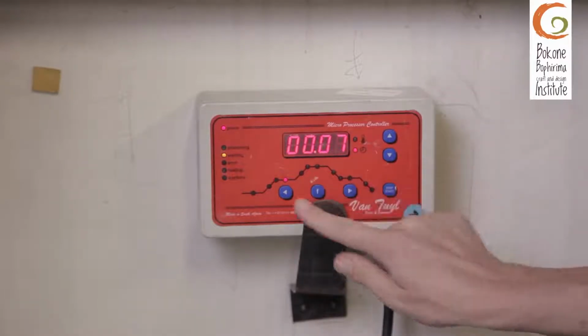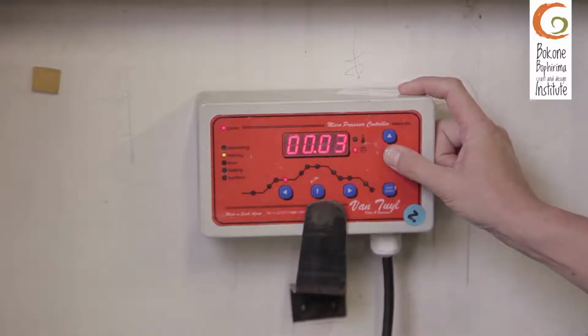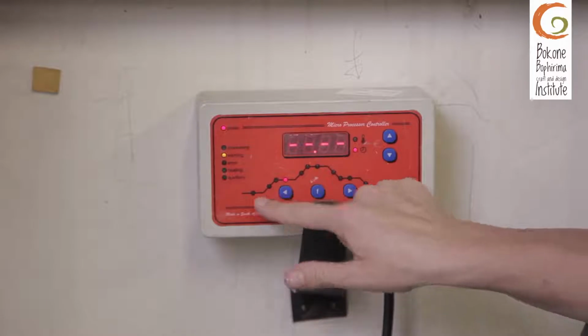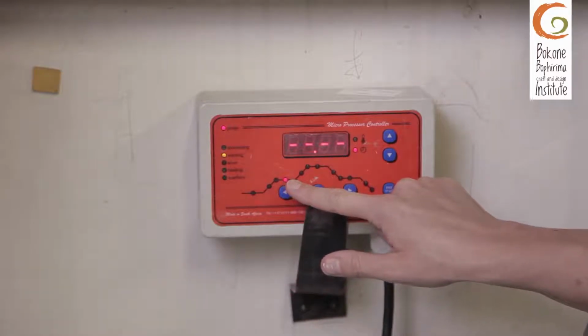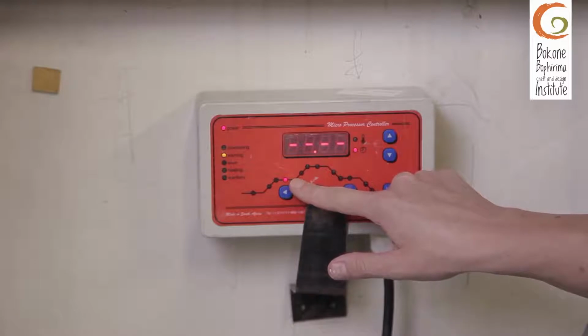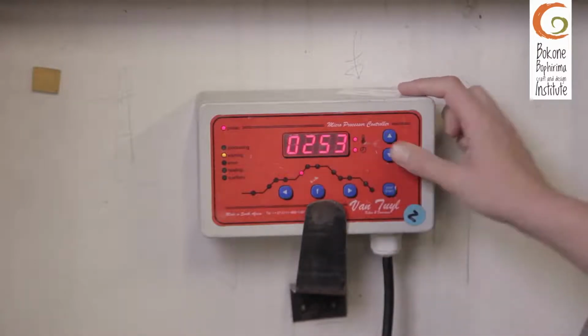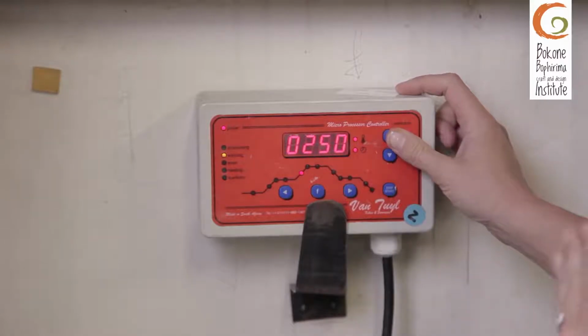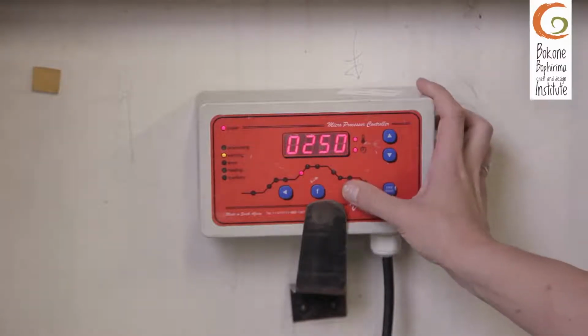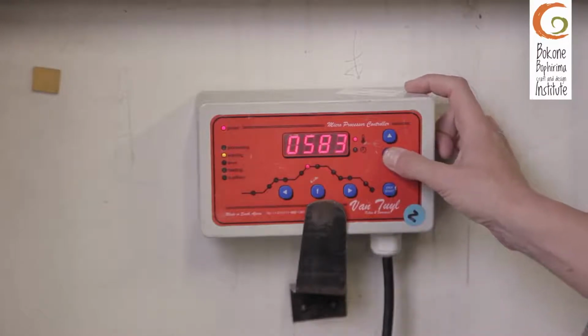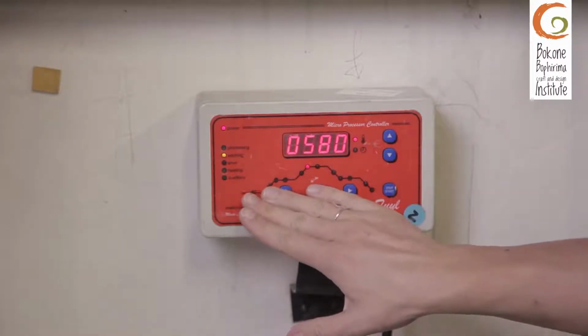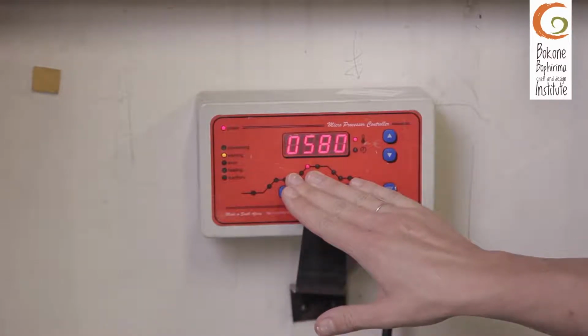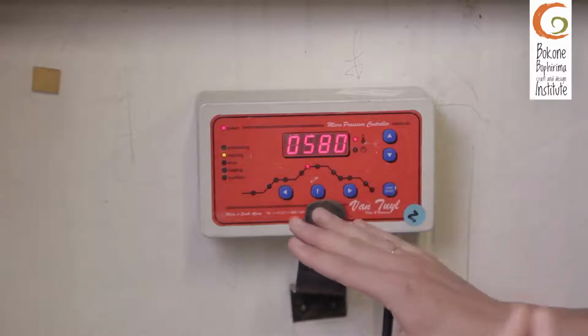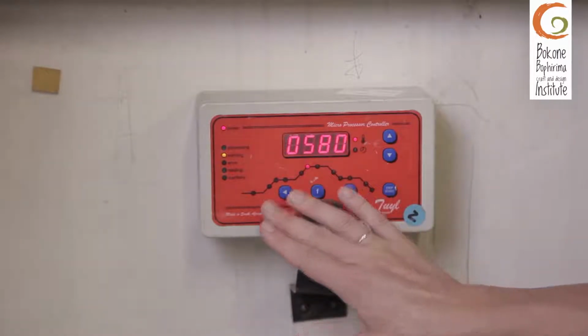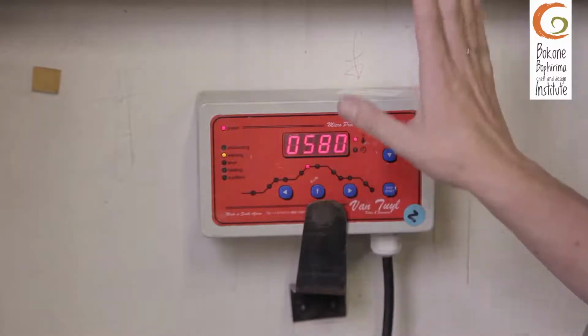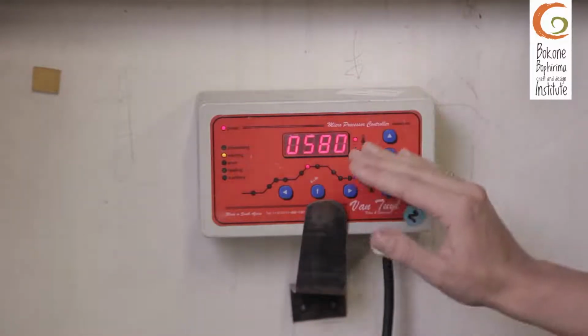So once I get to 300, I'm actually going to put in no delay here. So it's actually going to go through 300, past that, and it's going to go up exactly the same temperature again. Let me just double check. Yes, I'm going to bring it up then 250 degrees, so slightly faster, up to my top temperature, which is going to be 580. Okay, so I didn't take my time at 300 because I don't need a delay there. Our glass is at quite a critical point. It's got a lot of tension there, so we're rather going to pass through and we're going to keep ramping up but at a slightly faster degree temperature up to 580.